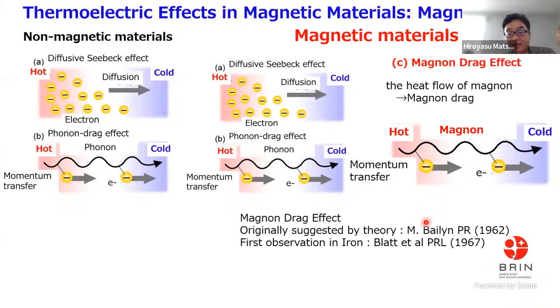So in the non-magnetic case, when we apply a temperature gradient, we can get the heat flow from electrons and the heat flow of phonons. But in magnetic materials, we have an additional heat current. This is the heat current of magnons. This figure shows the heat flow of magnons. When we have the magnon-electron interaction, we have an additional origin of the thermoelectric effect. This is the magnon drag effect. The magnon drag effect was originally suggested by theory. Bailyn suggested this magnon drag theory, and Blatt first observed the magnon drag effect in iron.